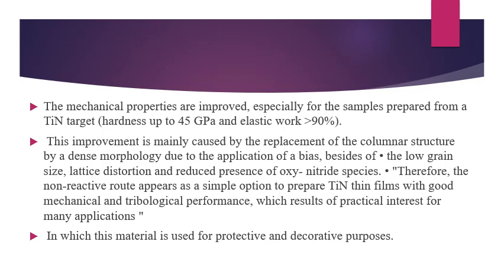This improvement is mainly caused by replacement of the columnar structure by a dense morphology due to the application of a bias, besides the low grain size, lattice distortions, and reduced presence of oxynitride species. Therefore, non-reactive routes appear as a simple option to prepare titanium nitride thin films with good mechanical and tribological performance, which is of practical interest for many applications. This material is used for protective and decorative purposes.